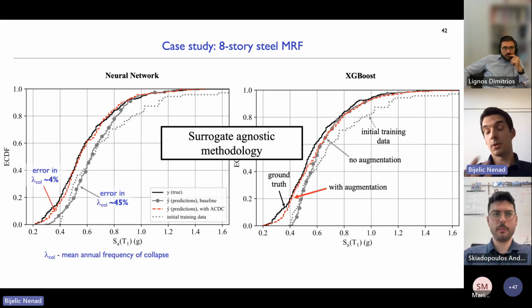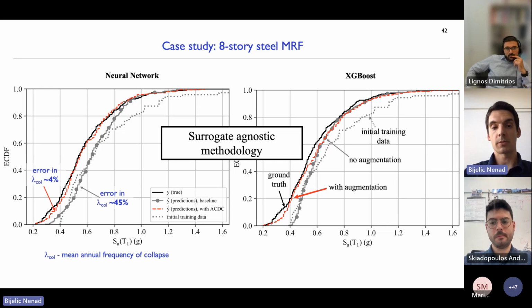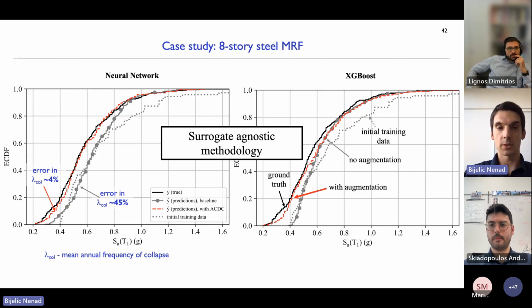And then, in terms of benefit and predictive capability, if we use only the initial training data and fit this neural network, the error in this error metric, called mean annual frequency of collapse, is about 45%. And if you add the augmented data, the error reduces to about 4%. And again, I just want to stress, no additional nonlinear analysis, no additional IDA was done, solely by massaging the data and augmenting it using the AC/DC procedure that I've shown.